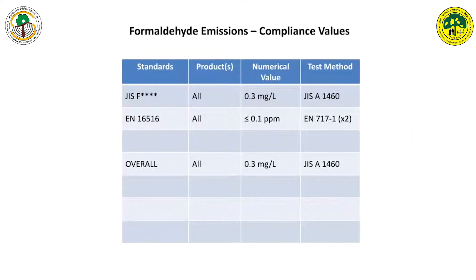As mentioned earlier, indoor air environments these days have fewer air exchanges. The earlier European chamber had an air exchange volume factor of 1. Considering new indoor designs where air exchange rates are lower because almost all indoors have a closed structure, with half the air exchange rate and multiplying the European chamber result by a factor of 2, there should be a maximum limit of 0.1 parts per million. Some seven or eight other countries have joined Germany in implementing the EN 16516 harmonized European standards.